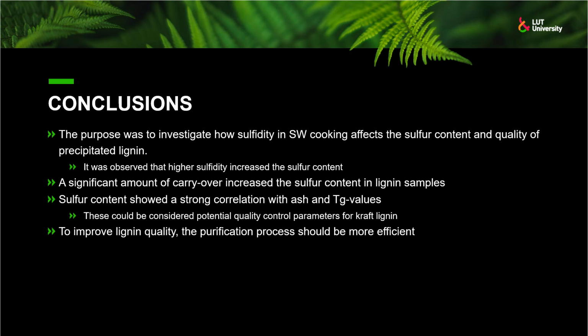Glass transition temperature and ash content appeared to be the most sensitive indicators of lignin purity. To improve lignin quality, purification procedures must be more efficient. Pressing and air-blowing steps should be applied to reduce impurities and increase the dry matter content of lignin.